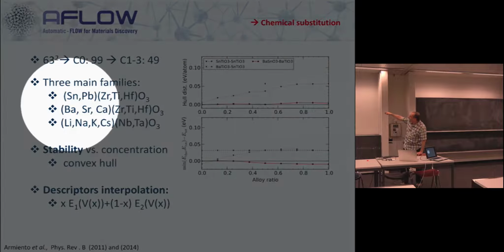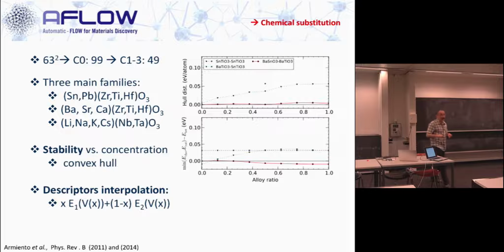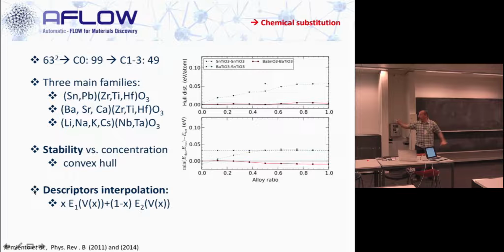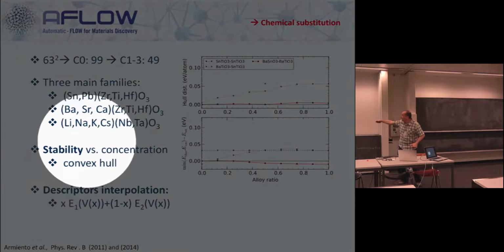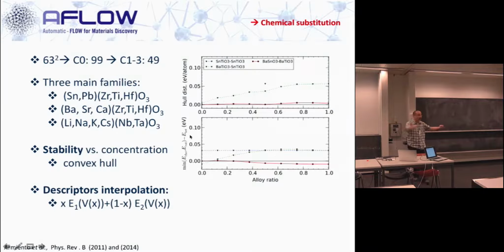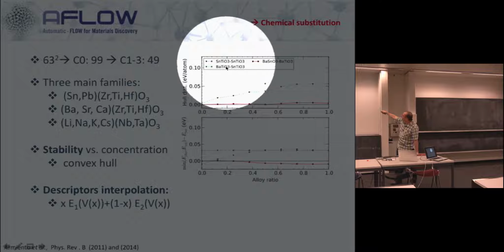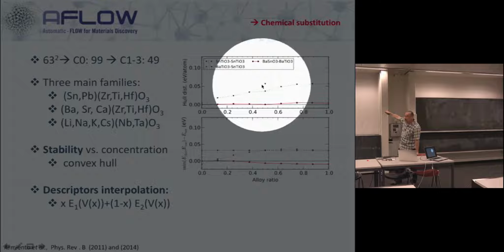And so based on this, we pushed a little bit further. We create alloys, right? And we didn't want to do gigantic supercells, relaxation, testing, and so on. We thought of doing this in a strictly high-throughput way where we actually look for descriptors. And what we came up with is a sort of interpolation between the property at the endpoints and study the stability and the tetragonality across the composition range. So this is an example. For instance, for the alloy between tin titanate and barium titanate, we saw that if you add in tin, you lose stability, but you gain tetragonality.